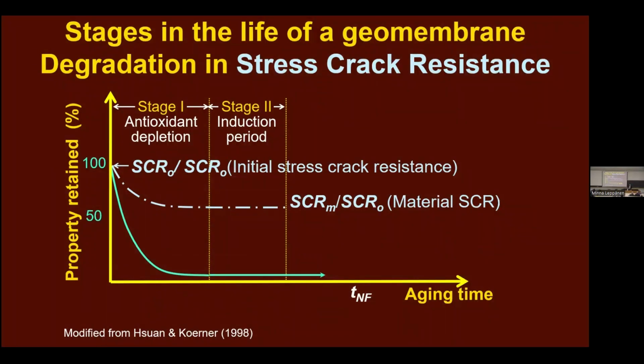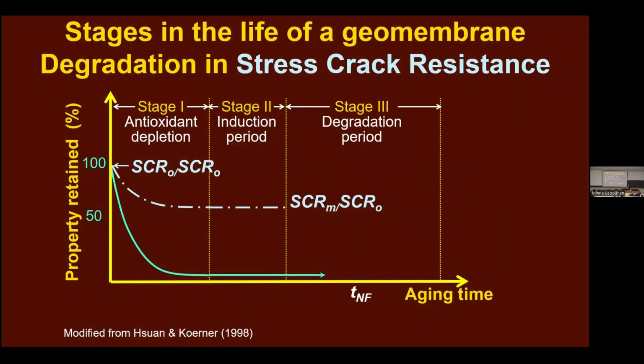Remember I told you stress crack resistance is a fiction. The value that you get on the manufacturer's sheet and that you get when you test it straight off the roll is only in part a material property. A lot of it's due to stresses built up in manufacturing. If you let those stresses relax, you go to the true value, SCRM. And that takes time. But that's what's going to control stress cracking in the field. So what we need to know is what is SCRM, and what we need to know is what are those antioxidants doing in contact with our fluid that we're trying to contain.